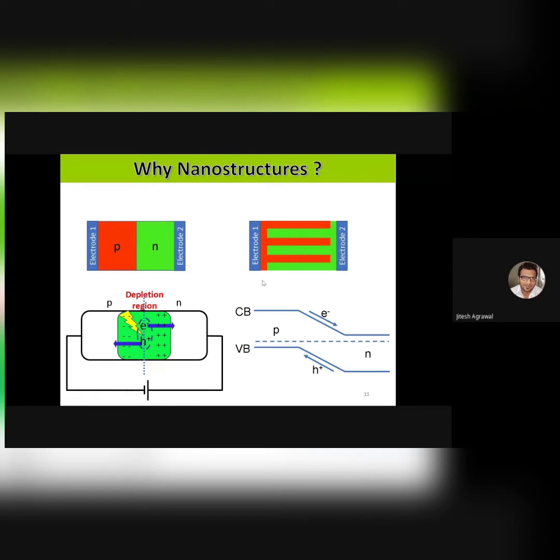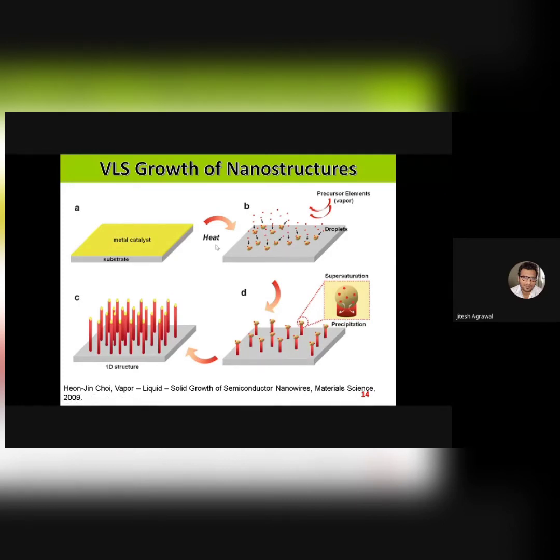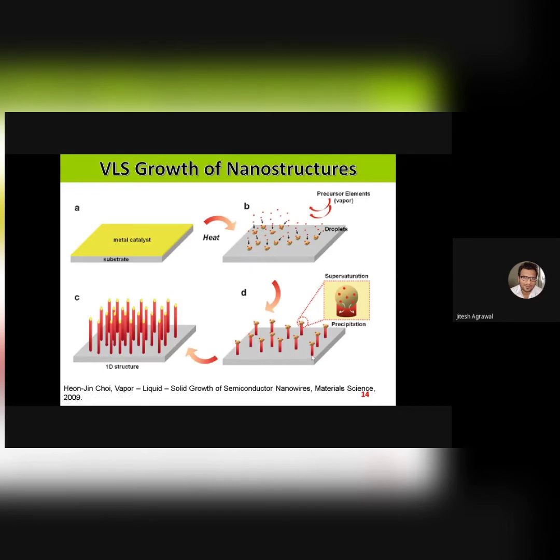How can we obtain metal oxide nanostructures? One method is VLS growth — Vapor-Liquid-Solid. First, the substrate is coated with a thin metal film. Then the substrate is heated at high temperature so that the thin metal film melts and forms droplets over the substrate. The precursor vapor enters the deposition chamber, where it diffuses into the metal droplets and starts to supersaturate. Once supersaturation is reached, it starts to precipitate down and deposit at the bottom while the metal droplet moves upward. This process continues and gives rise to nanorod-like structures. You can control the diameter of the nanorods by controlling the film thickness and heating temperature.